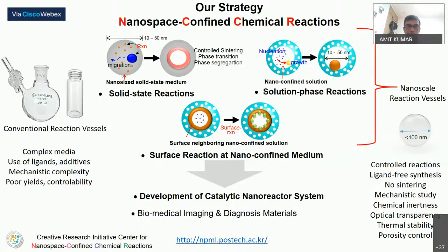All these approaches are very different from the conventional ligand-based synthesis of nanoparticles. In ligand-based synthesis, you add various additives, reducing agents, and many other complex conditions, and we don't understand in the bulk reaction media what the actual mechanism for nanoparticle growth is. Importantly, the resulting nanocrystal is occupied by complex ligands, and for catalytic applications the surface ligands can interfere during the catalytic reactions. But our nanospace-confined chemical reaction approach results in surfactant-free nanoparticles, and those are very useful for catalytic nanoreactors.